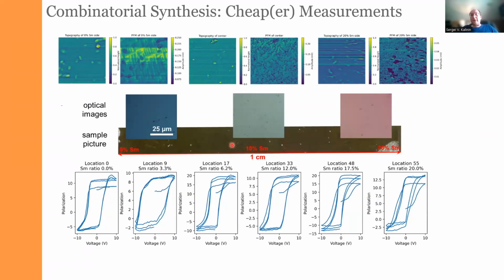Obviously, in order to do that, I need to postulate that there is some relationship between the signals that I measure with the atomic force microscope and the observations that I'm doing in the electron microscope. In this case, I know that this is the case because ultimately the AFM measures something related to polarization. And we have domains if there is a polarization. We don't have domains if there is no polarization. For the hysteresis loops, the relationship is more complicated because hysteresis loops can form because of several mechanisms.